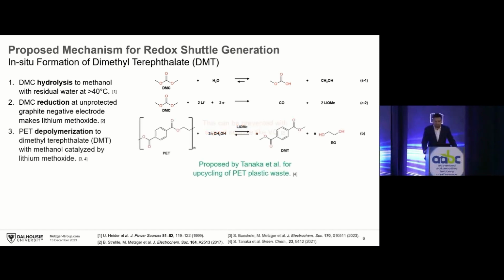So if you have those two species, methanol and lithium methoxide, then you can, in fact, depolymerize PET. There's a very interesting paper from Japan where they upcycle PET plastic waste by adding methanol and lithium methoxide as a catalyst. And then you can break down that polymer into its monomer, which is our DMT molecule that we found in the battery cells, and ethylene glycol.